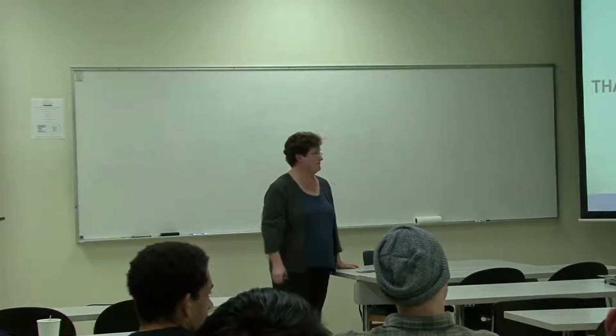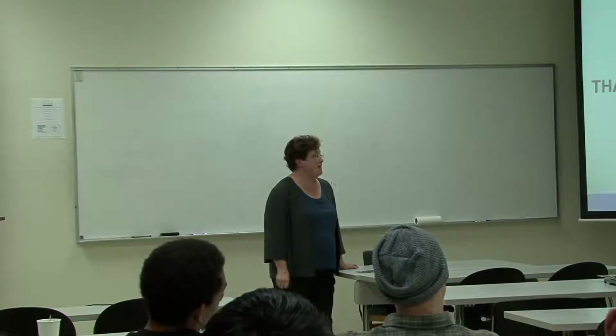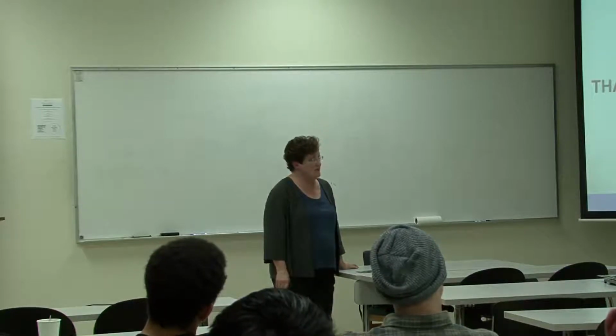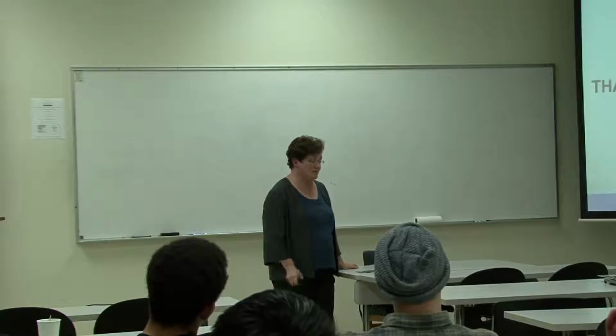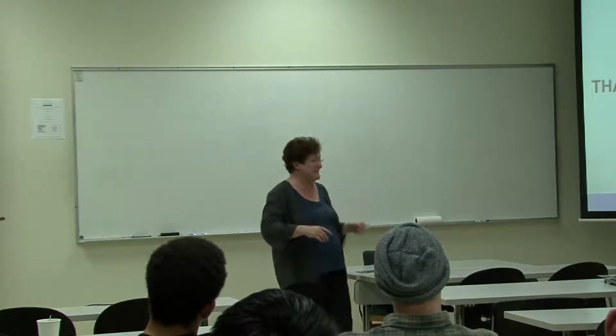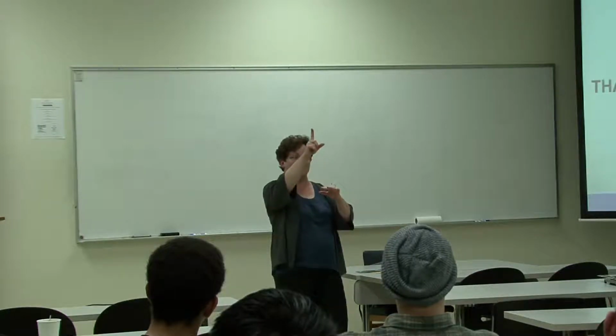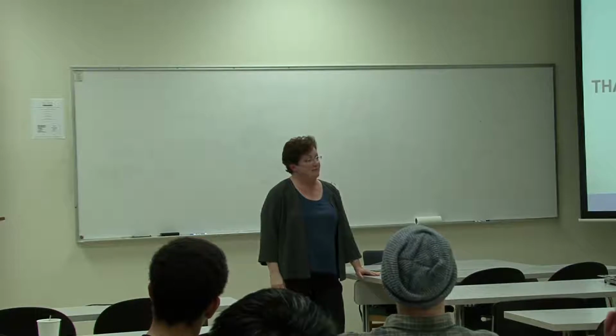So, yeah. Do you still have trouble with tin whisker growth, or is that a solved problem? We have not seen any on our products. There are people that are still worried about it a lot. What this is, I left out that picture, so I was thinking about it. When you have stressed tin, pure tin, especially bright tin that is nice and shiny, it tends to be higher stress, and with that stress, it needs to relieve it. The way it relieves it is one of the grains of tin starts extruding out a whisker, like squeezing toothpaste out of a tube. It just keeps growing and growing until it shorts something. And it's very thin, so usually after it's shorted, it burns away and you can't see it.